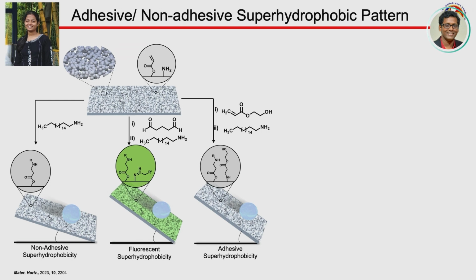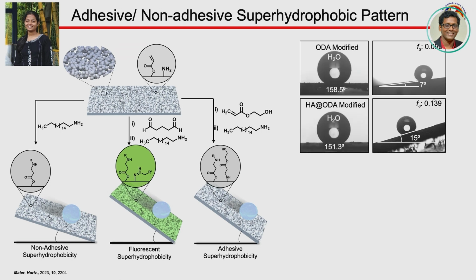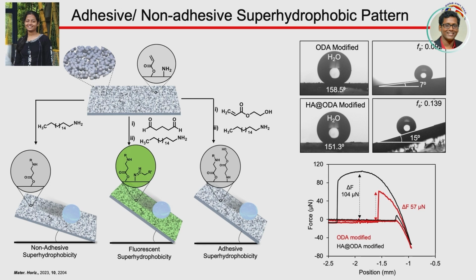And then you take another modifier, a small molecule that has an acrylate group and a hydroxyl group. So hydroxyl acrylate, which can readily react with the amine group, and then it can make this interface adhesive, maintaining this extreme water repellency. So water repellency remains above 150, you can see the roll-off angle drastically changes, almost twice, and you can see the fraction of contact area of solid and liquid is also significantly changed. Not only that, you can precisely measure the force of adhesion between the beaded droplet and solid surface, that is almost a twofold change.